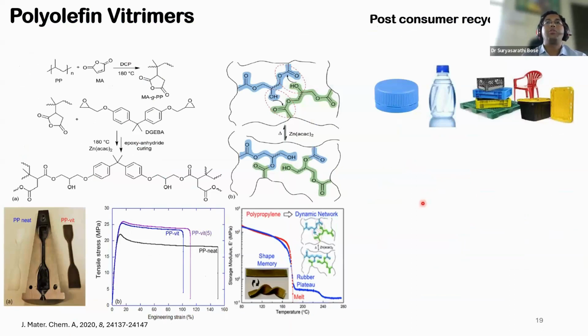So before I get on to show results from my lab, I thought let's show you some of the results from the literature. This is one of the studies on polyolefin vitrimers, which has been published in the Journal of Materials Chemistry A. You can see that the starting material is polypropylene, which could be PCR polyolefin as well. You have maleic anhydride, and with little temperature and DCP, you can actually graft the maleic anhydride onto the polyolefin chain. This step is very important in polyolefins because polyolefins lack any chemical bonds that can actually bond with any other chemicals. So it becomes very, very tough to graft anything on polyolefin because there are no functional groups that are available. So once you start with this material, then there are n number of materials that can help you to form dynamic bonds.